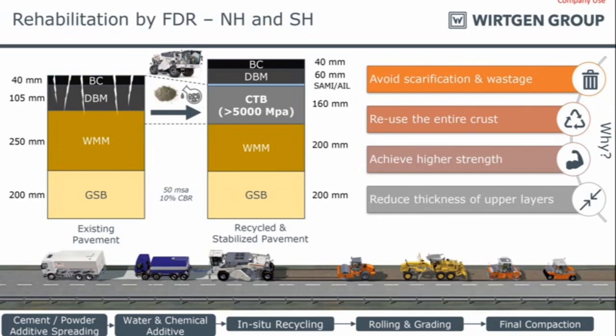Coming to NH, National Highways and State Highways, we are already executing it. So since it consists of fresh aggregates, we call it a CTB, cement treated base layer with a very high modulus of 5000 MPa. Then again, we provide an aggregate interface layer on top of it. And we seal it with two coatings of asphalt because we are working at very high traffic volumes. The train of equipment is similar to that of rural roads. We have a similar set of equipment.